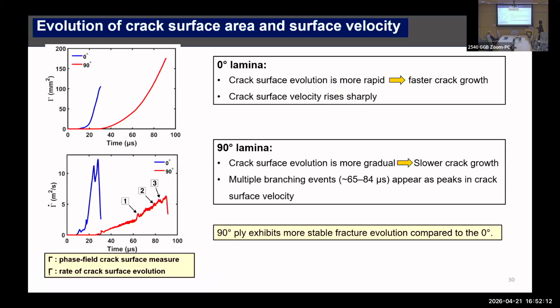So again, we calculated the crack surface area, in the phase field sense, the regularized crack surface, and the speed or velocity of this crack surface evolution. So gamma dot. And for 0 and 90, if we compare, same story. 0 degree is much faster, much quicker, and much more drastic. You see, it's like an unstable peak in the velocity and then it comes down.